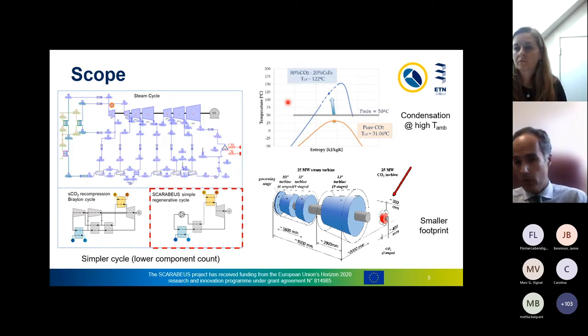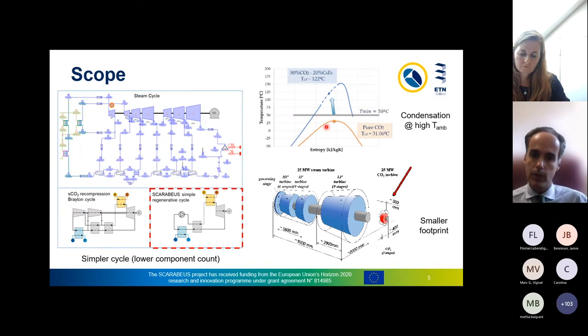So that is why we've considered that maybe if we add certain dopants to CO2 and we're able to shift the critical point to a higher temperature, then we can still have condensation in the cycle or even get close to the critical point, therefore have the liquid-like behavior of the working fluid. And that is what Scarabeus is all about. And that is what you can see here.